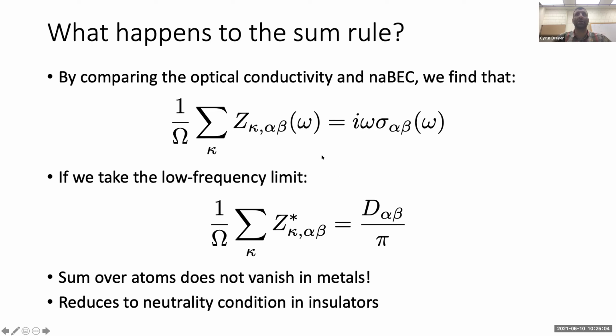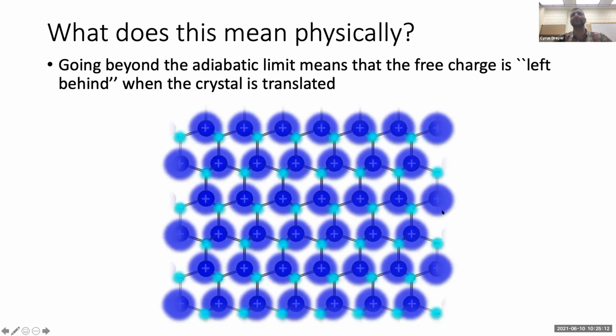So as I said, I'll give an argument about why this is the case in a second, but first, what does it mean physically? Physically, what we can think of is that, as I said at the very beginning, the sublattice sum of the Born effective charge, the perturbation in this case, is basically taking the whole crystal lattice and shifting it. And if we do this at a finite frequency, then there's some charge that cannot keep up with the shift in the lattice that could come from a photon frequency or similar.